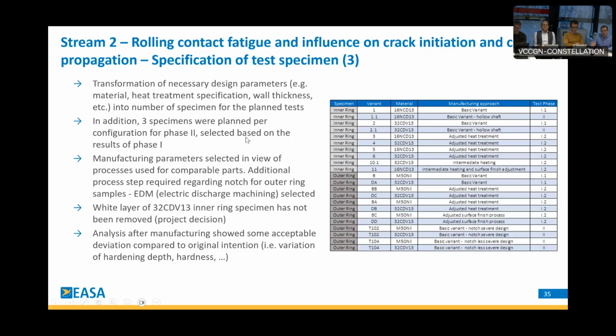The table on the right side gives you a rough overview of the specimen called inner ring and outer ring. The inner ring is actually the shaft specimen with the several variants that you see here that were tested. The materials range from 16NCD13, 32CDV13, but also M50. And you see here the manufacturing approach from a basic variant to adjusted heat treatment and so on. And you also see here which specimen in which condition was used for which test phase.